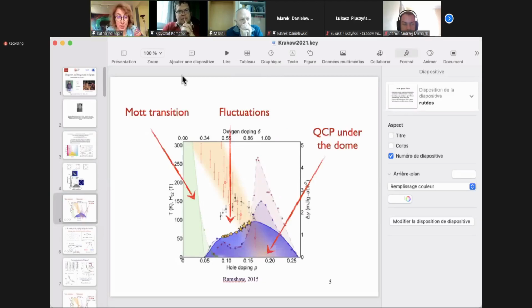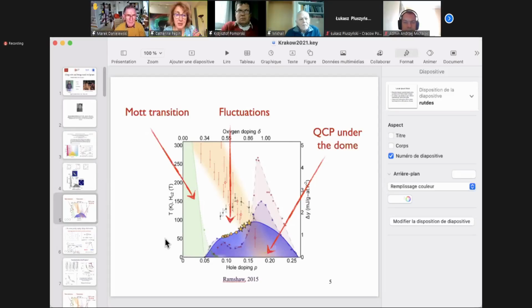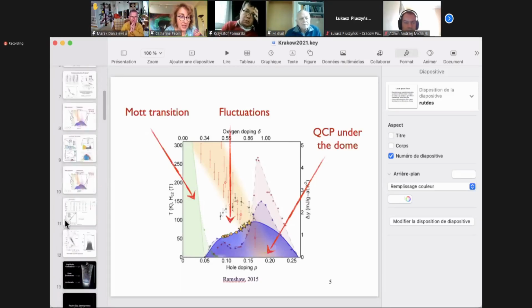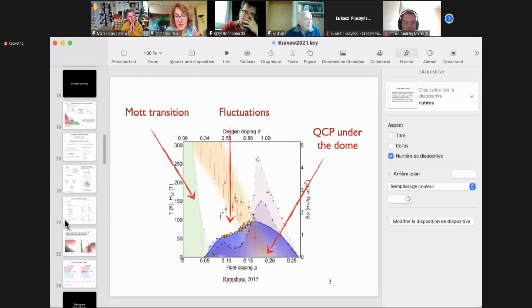Yeah, actually, this is a very good question. I'm sorry, in my review, I didn't address this topic. The pairing mechanism is something that we almost have a consensus on now. It should be due to antiferromagnetism, which naturally predicts a D wave superconductor. Maybe there's a bit of S wave still under debate, but the idea here is that the pairing is due to antiferromagnetic interactions, which provide a very nice D wave superconductor and also provide actually charge density wave. If you take the toy model we had, for example, here, but this is a consensus. There are very few consensus points on these compounds. It's one of them. It was highly debated in the early days, and it was a huge fight between S wave and D wave.